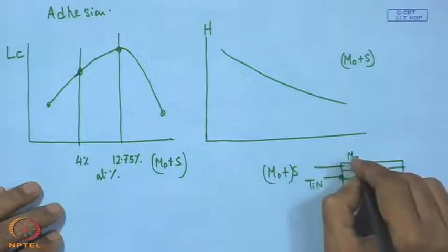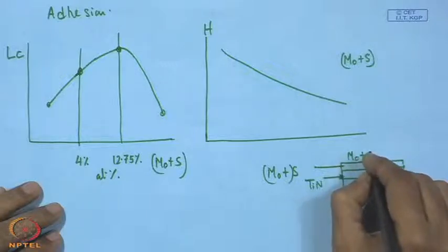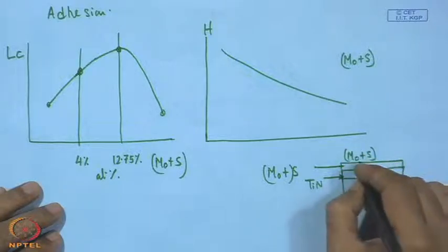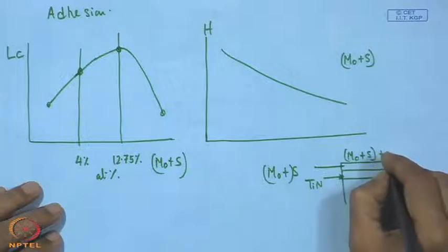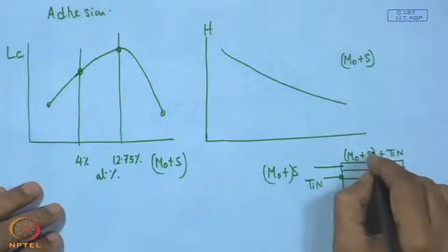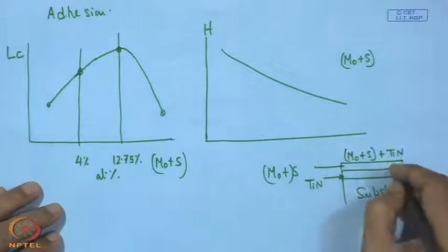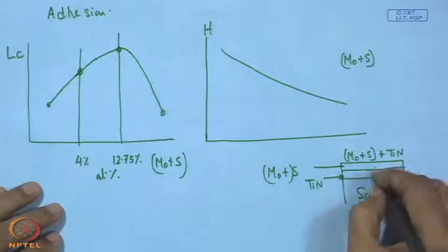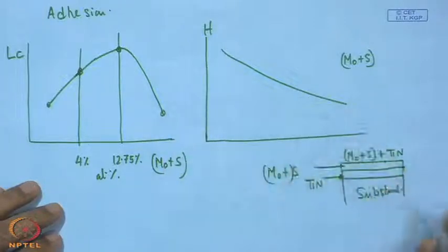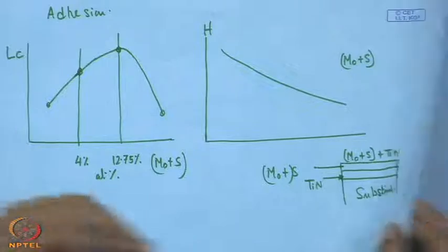So, here we have MoS plus TiN, which is in the form of MoSx plus TiN. So, the higher the percentage of this one, naturally when we measure the hardness, it has its own influence, and that is why it has a drooping curve.